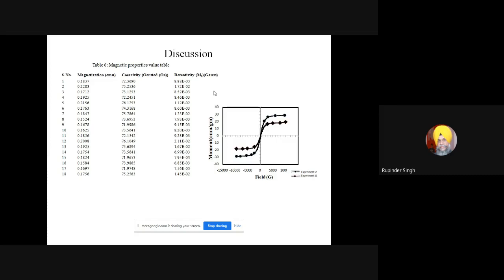Then I can switch off the electric field, but I can have a permanent assembly. Now after a few days, if I am interested in some other shape, I can again switch on the power, and I can disassemble and think of a new assembly. For that purpose, I am interested in how much of the magnetic field will be required. Magnetization is how easily I can magnetize. Then if I switch off the magnetic field, how much retentivity will it have once the magnetic field is over. The coercivity is the value required if I change the direction of the magnetic field, or to make it zero, how much opposite direction magnetic field I have to apply. So those are the three things that we observed from this BH curve.